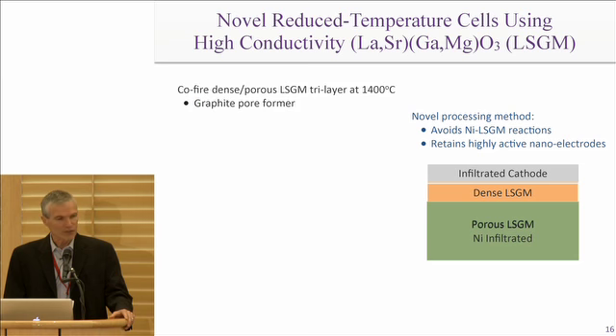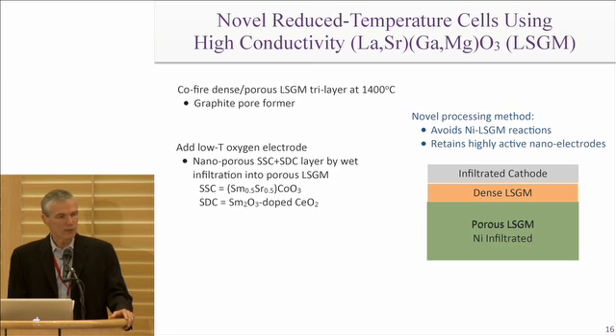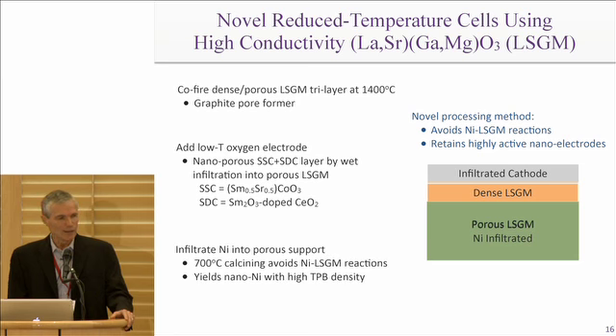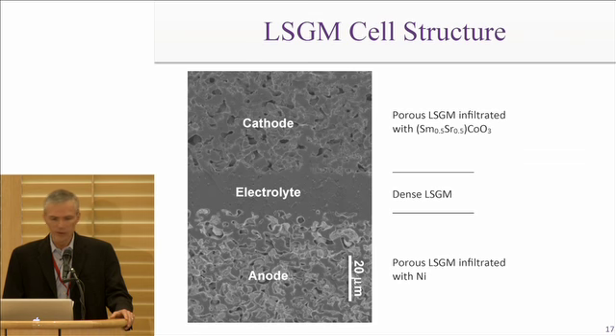Okay? So we came up with a scheme for making these things in which we actually start out with a structure that looks like this. It's all LSGM. We can take this and fire it at very, very high temperatures, 1400 degrees centigrade, to produce this structure. And then later on, we can introduce some of these materials at lower temperatures and avoid some of the reactions. Okay? So for example, then we infiltrate in a nanoscale cathode material. We're using, for example, samarium doped strontium cobalt oxide, a very active oxygen reduction catalyst. On the other side, the fuel side, we're infiltrating nanoscale nickel onto the support, which also provides a highly active structure.